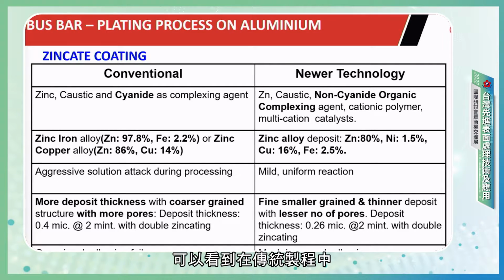In the conventional process we were doing alloying with only iron or copper. In the newer technology, we are using nickel, copper, and iron along with zinc. So it's a tri-alloy zincate, with a composition of approximately 80% zinc, 1.5% nickel, 16% copper, and 2.5% iron. Formulations are very stable with this composition.